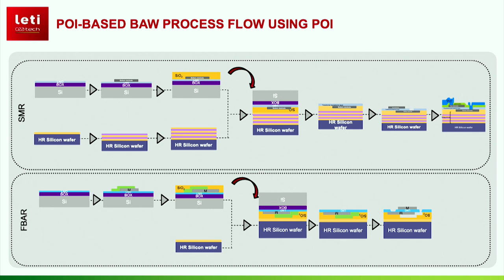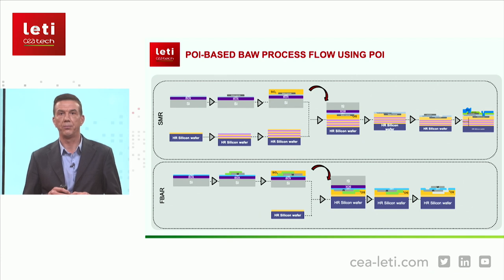Separately, the Bragg mirror is fabricated on a high resistivity substrate. Then comes the bonding step, followed by the grinding of the handle wafer and its box, exposing the piezo layer. Finally, the top electrode is deposited and the sacrificial layer is removed. The last step consists of the pads and passivation layer deposition.